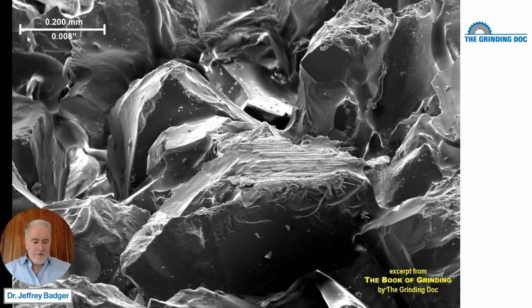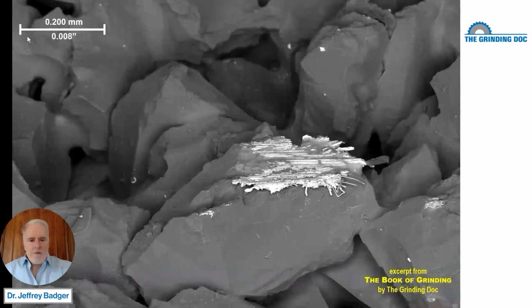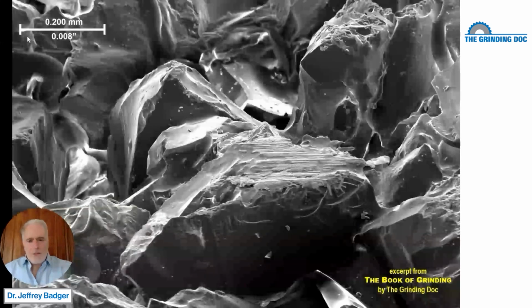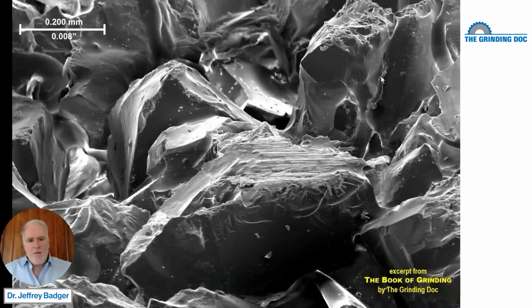And these are some of the SEM photos, along with Philip, a German guy at Chalmers. He also supervised the project. So what we have is an aluminum oxide wheel dressed with a diamond roll. And what we see here is a flat, dull grit. So that's a flat, dull grit created not from grinding, but from dressing. In fact, most dull grinding wheels in the world are not dull because of grinding, they're dull because of dressing. They dress the wheel dull.